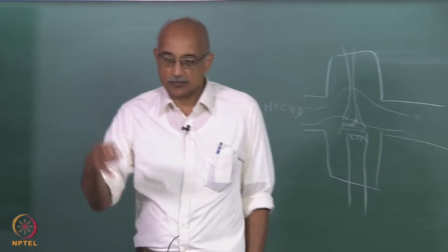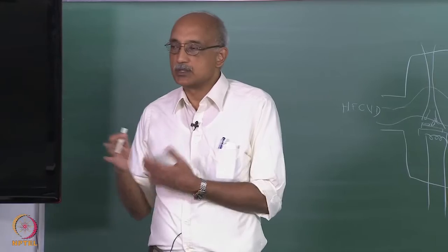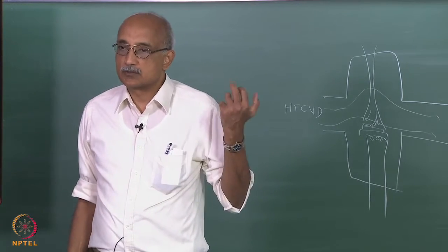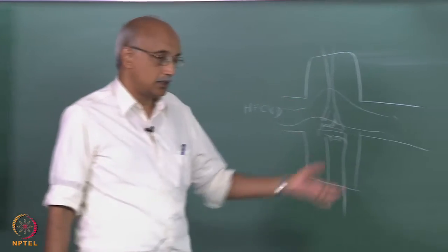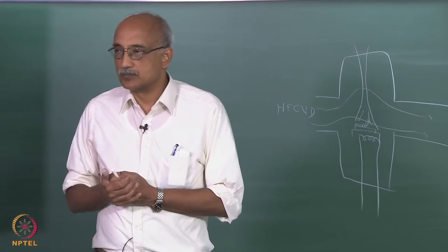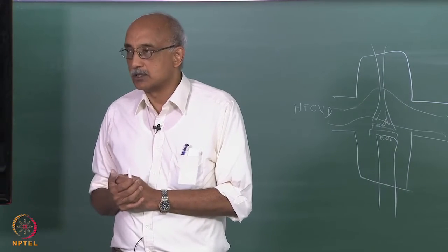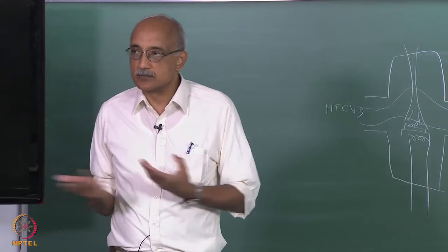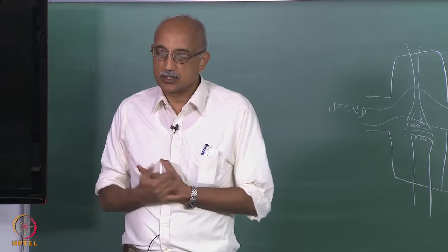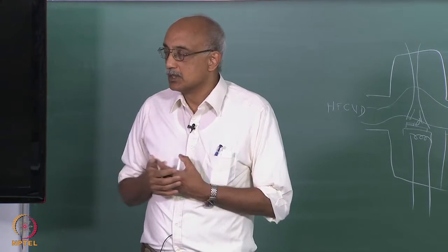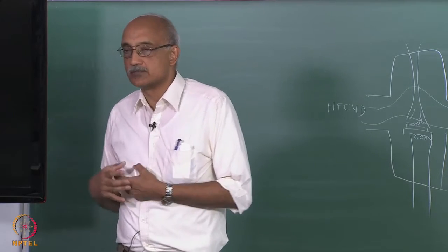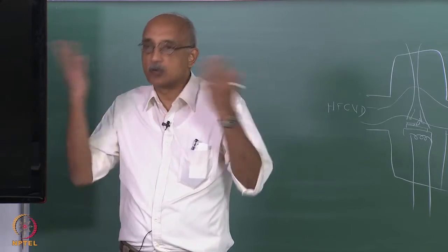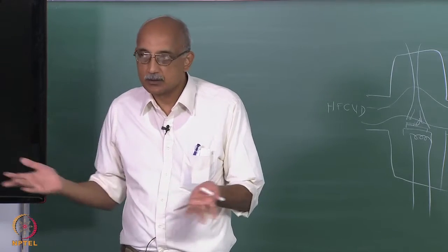So placement of the filament is one issue. The second is controlling the flow in the system. Now this type of reactor is naturally three-dimensional. The species that you are generating, there is no preferential direction for them to go. So it's a diffusion controlled reactor typically. Diffusion is a random walk process, so the direction in which the dissociated molecules move is entirely random. There is no preferred orientation of motion, which implies that you are not really directing them towards the substrate. You are allowing them to go wherever they want to go and then hoping that some of them will impact the substrate.